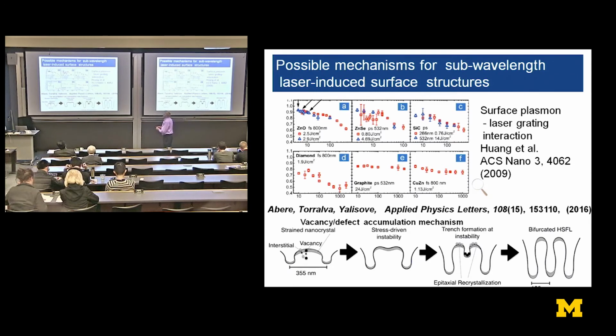And that coupling can actually modify the potential in different parts of the optical field. In other words, imagine the laser as a sine wave. On the peak of that sine wave, you have a very high field, and that can drive the potential changes, interatomic potential changes, whereas at the minimum of that field, that will leave part of the structure undisturbed, and that's what we see here.